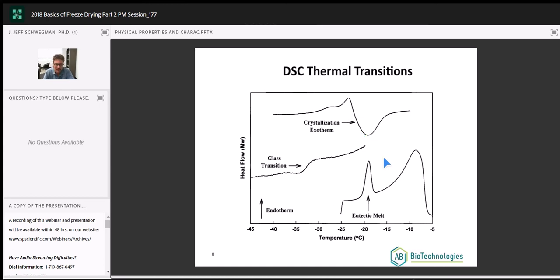Okay, great. Now the temperature that we use. So for a eutectic, the software on our TA instruments DSC draws a tangent to the leading baseline, a tangent to the front end of the peak, and where those lines intersect is what we report as the onset of the eutectic melt. Glass transition, there's several temperatures we could report. Generally, most widely accepted is the midpoint. So we tell our computer to draw a tangent to the leading baseline, a tangent to the trailing baseline. The midpoint between those lines is what we call Tg prime.